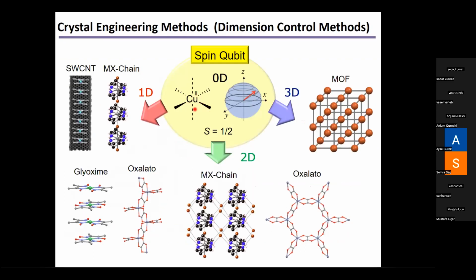So then, the next target, the copper complex. Usually a bulk copper complex shows antiferromagnetic interaction. However, if the copper molecule is doped into a diamagnetic 1-dimensional, 2-dimensional, or 3-dimensional host, so diluted, then we detect only one copper ion. This should show slow magnetic relaxation and should show spin qubit behavior.